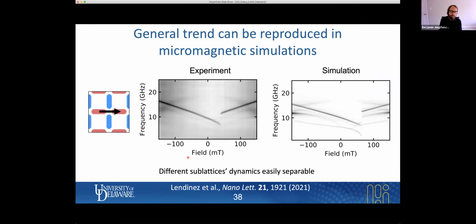So let me show this to you here. Again, nickel iron horizontal elements, cobalt iron vertical elements. I'm applying a field angle of 0 degrees. We show here the experiment on the left and the simulations on the right. We get a pretty good agreement here. And the beauty of the simulations is we can easily identify the sublattice dynamics and identify which lattice corresponds to which mode. So red is permalloy and blue is cobalt iron, and we can now know which modes correspond to what.